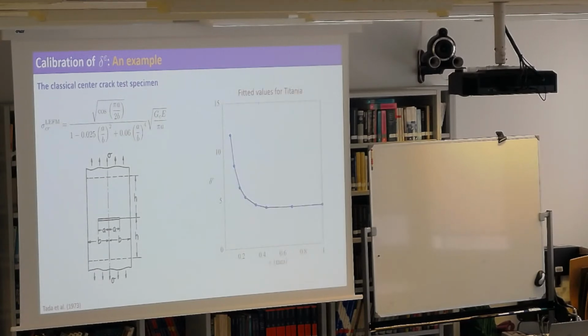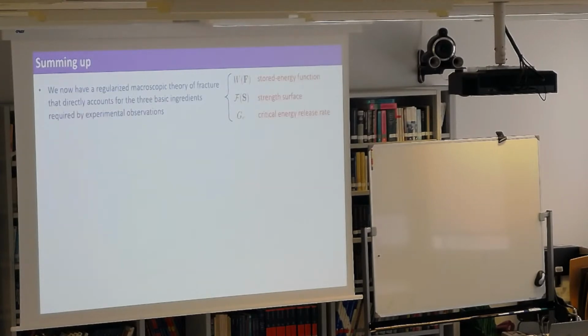And the value that does that for, let's say, titania, the material I showed you before, is this delta epsilon. And this is how delta epsilon behaves as epsilon goes to 0. Okay? This is just a numerical calibration. And for the time being, this is the best we can do. So there's more work to be done here. But the great news is that we can calibrate everything now, and that it seems to work. And I'm going to show you, well, we have done actually many, many comparisons. Everything has checked out. So I'm going to show you just two simple calculations.